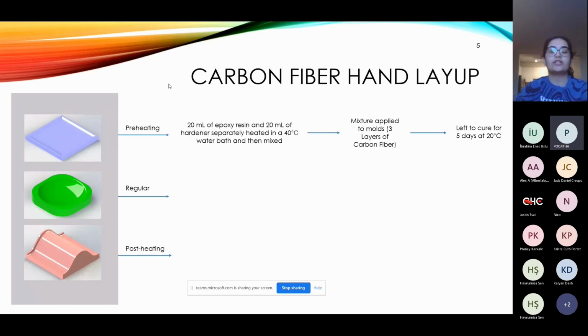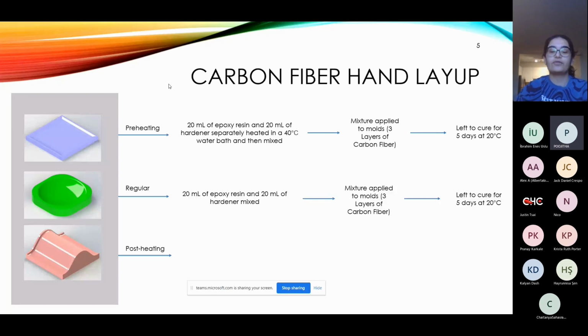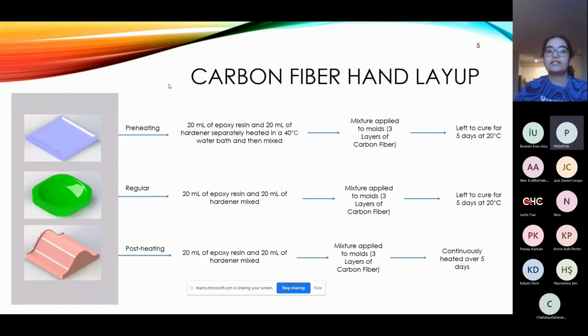For all conditions, a generous amount of wax release agent was brushed onto the molds. 3 layers of carbon fiber were applied per mold, and the molds were allowed to cure for 5 days. For the preheating set, 20 milliliters of epoxy resin and 20 milliliters of hardener were separately heated in a 40 degrees Celsius water bath and then mixed. The heated mixture was thinly applied to the molds and between the carbon fiber layers, and the composite was left to cure for 5 days at 20 degrees Celsius. For the regular set, there was no preheating of the epoxy resin and the hardener. For the post-heated set, the carbon fiber parts were continuously heated over their curing time of 5 days.